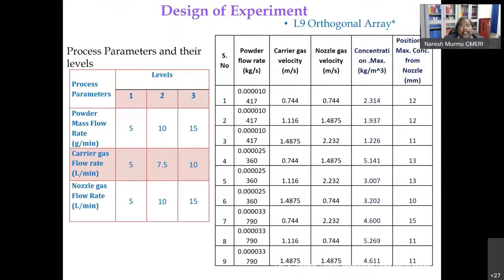So we moved on. Then what we did, second, is an interesting design of experiments. We use that to get some optimal values. It is just a parametric study on the process parameters, of course. As you know, it is very long. An L9 orthogonal array was taken that time, and the powder mass flow rate was taken as 5, 10, 15, carrier gas 5, 7.5, 10, and nozzle gas 5, 10. These are the parametric studies we have done. And from there, basically we got some important information about the maximum concentration in the particle concentration.